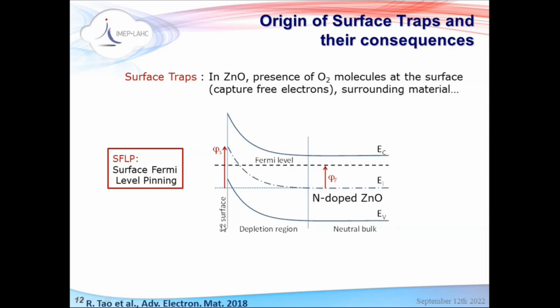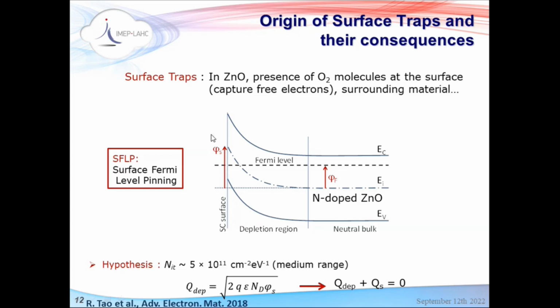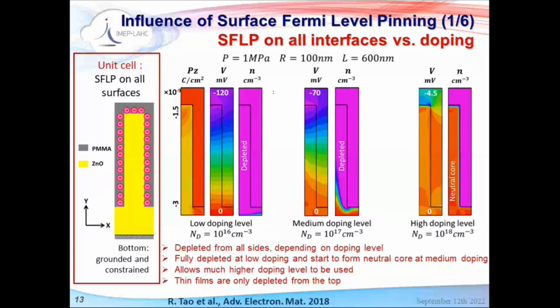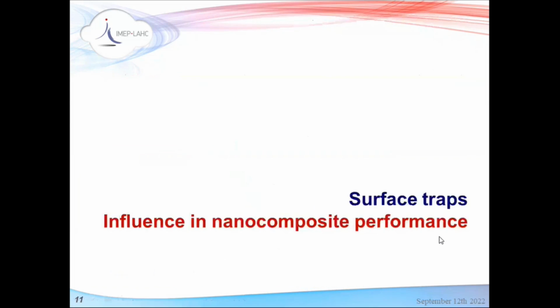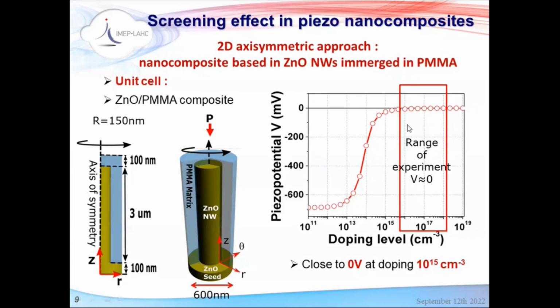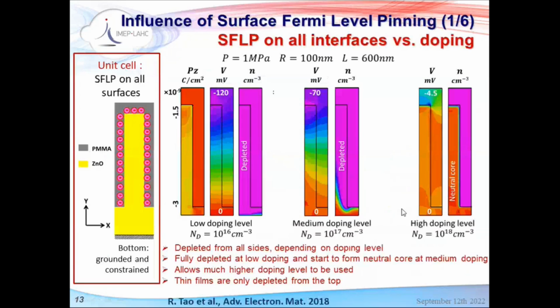All right, I will not go into the details about the equations, but we can calculate the surface charge and put it into the model as a boundary condition, with some hypotheses about the density of these traps that capture electrons. So I want to show you what happens then. If we put these surface charges or these surface traps around the nanowire, you will have a depletion zone from the top and from the borders. So I represented it in these images. So here you have 3 doping levels: low doping, medium doping, high doping level, that actually corresponds to this red square that I showed you before. All right. So what I show you is the potential.